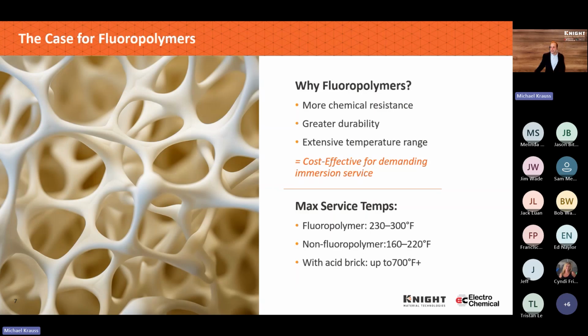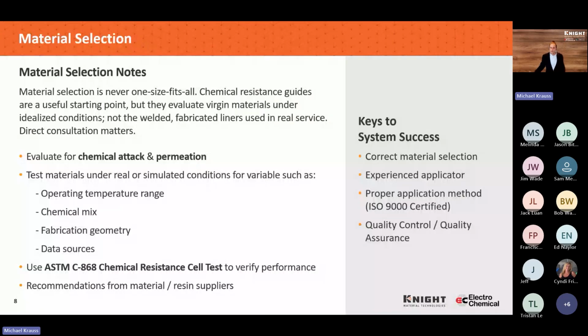Material selection, again, is a really challenging source. I mentioned briefly that you must see conflicts with different guides, say for PVDF. And you have to understand there are two main suppliers of PVDF resin in the Western world. And the chemical resistance guides that are out there are very different. Once you understand the reason behind it, it makes sense. The first supplier's PVDF is the highest performing material they make. And they've done extensive work and research with adding additional grades and developing a huge database to know exactly where and how far they can push PVDF. And they tend to be aggressive and push it to the exact limits that they can get away with, because that's what they have.